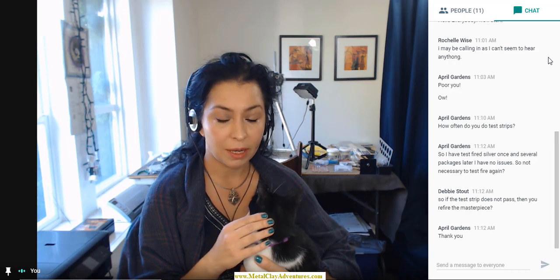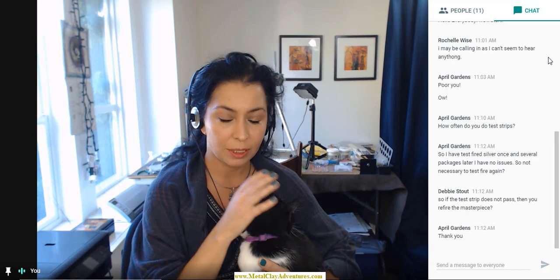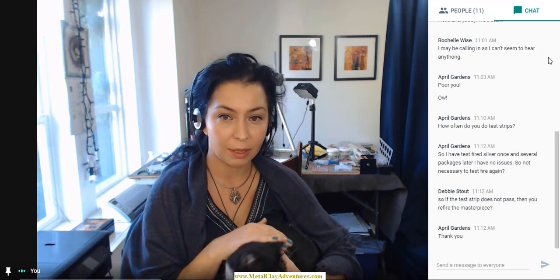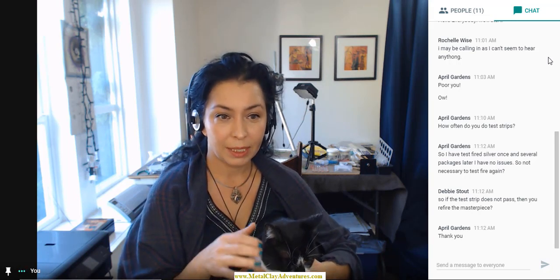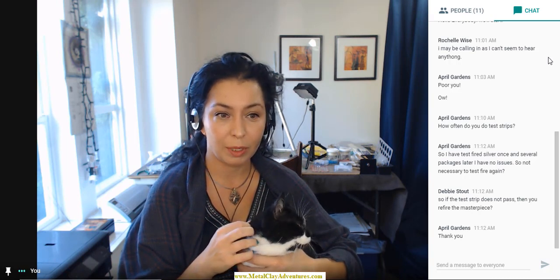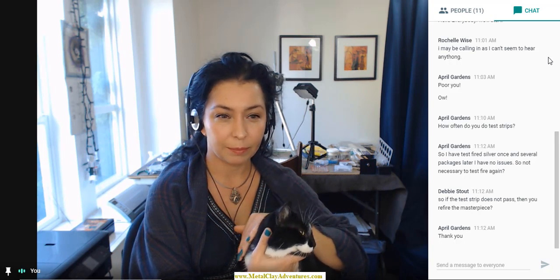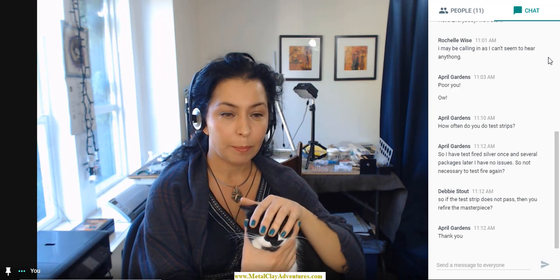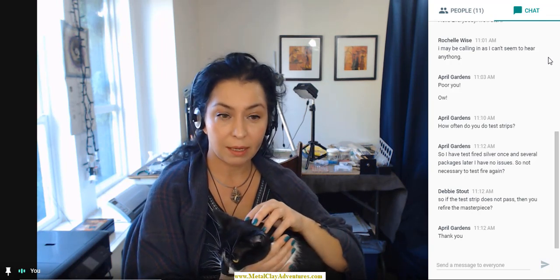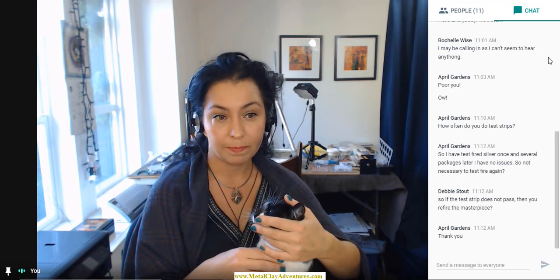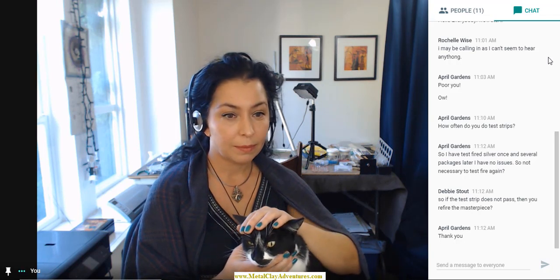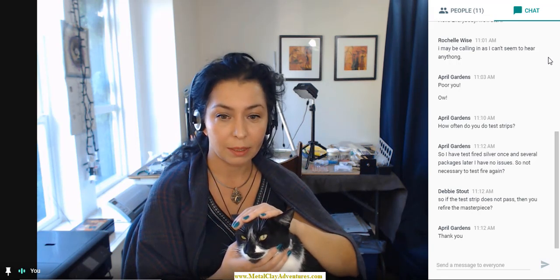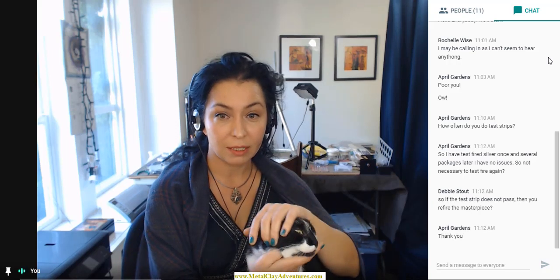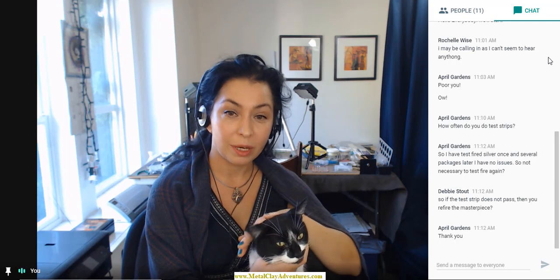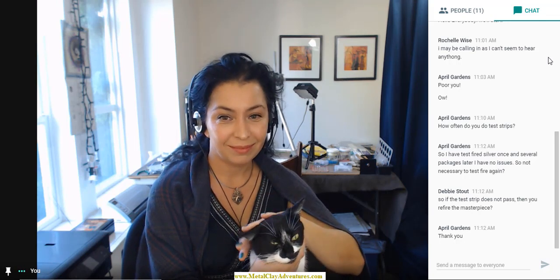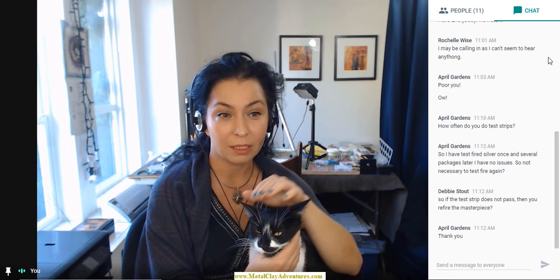April, I would give you an advice. If you are using silver which is manufactured by big companies, let's say Mitsubishi, which manufactures PMC, I don't think we need to test fire repeatedly, because they are very consistent about their metal clay. But if you are firing metal clay from small manufacturers, you need to test fire every batch, because according to my experience, I had some interesting results when test firing. One batch was good and another batch just didn't turn out. So better test firing every batch you are getting from small manufacturers.